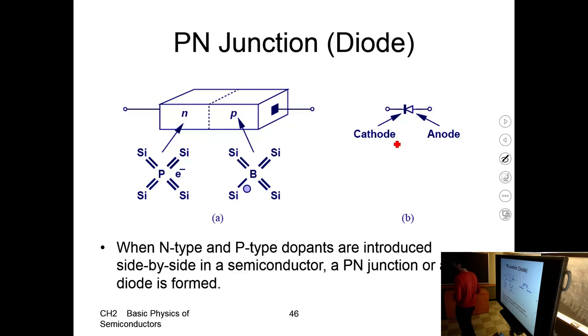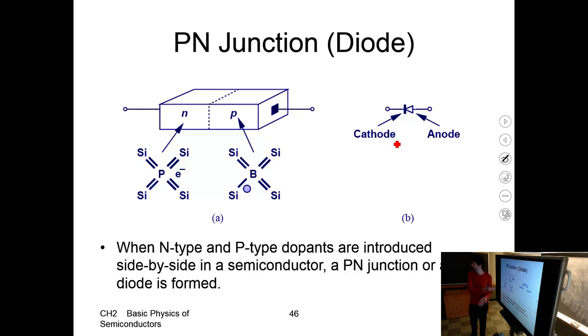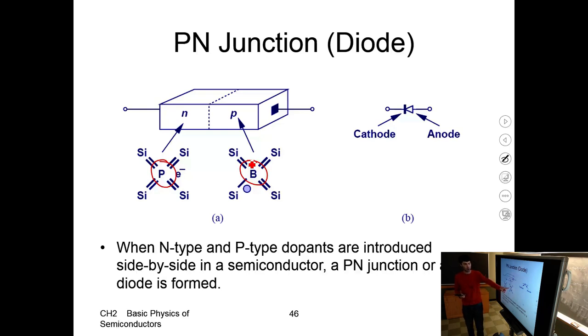Another important element is a junction between differently doped regions of the same semiconductor — most commonly silicon. What changes as you go along the junction axis is the doping. You put together regions of n-doped silicon and p-doped silicon. In n-doped silicon, phosphorus atoms bring extra electrons, giving a higher density of electrons. In p-doped silicon, boron atoms create extra holes — one missing electron per boron. This structure is already a device — it's called a diode.